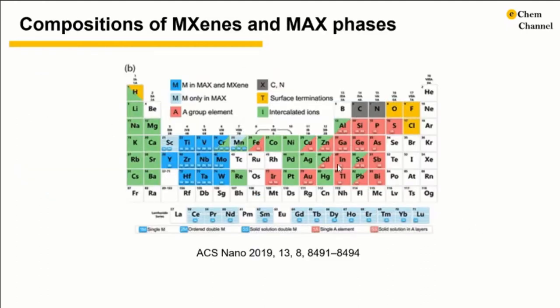Here is a periodic table showing the elements that are involved in the MAX phases and MXene family. The rush in synthesizing new ordered 2D carbide phases brought excitement to the MAX phase research community. Since 2017, researchers have synthesized about 30 new ordered double transition metal MAX phases and explored their properties. However, the elements with blue striped background are only reported in MAX phases, and their MXenes have not yet been synthesized. The elements on the red background are the A elements in MAX phases that can potentially be selectively etched to make MXenes. For now, the majority are etched from MAX phases with aluminum and silicon as A elements.